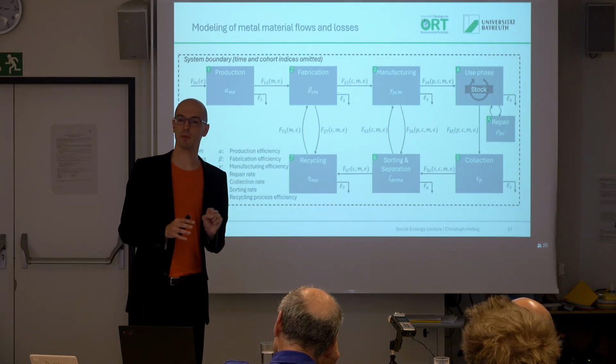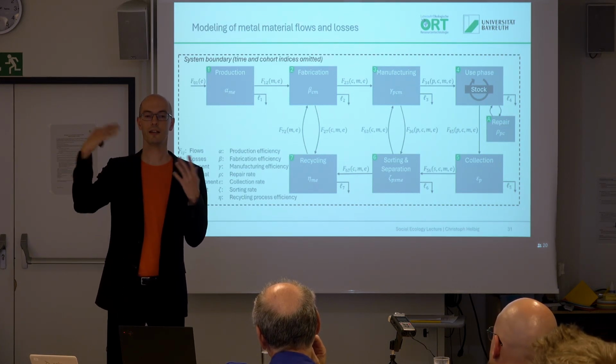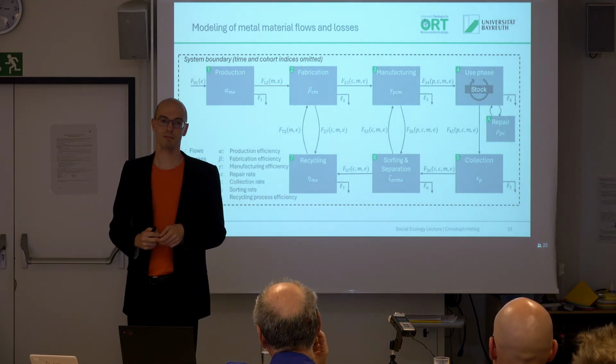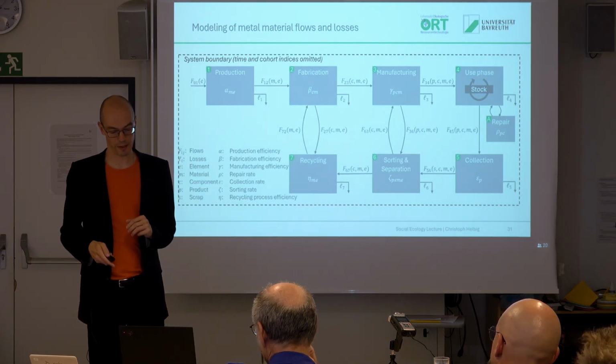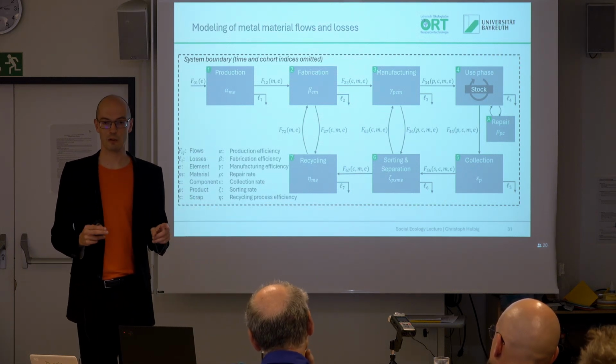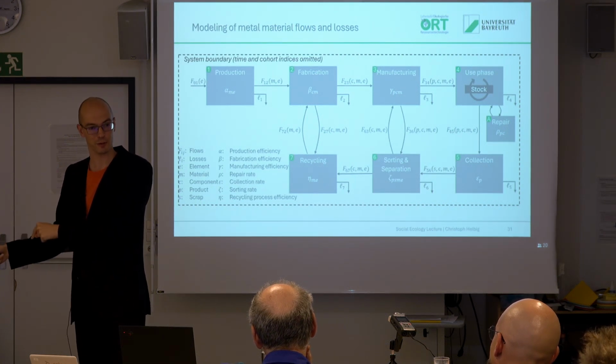Quite a bit of that we can recycle from EAF dust. So from electric arc furnaces, the zinc goes into the dust, and there we can get it back. With many other materials, they are much more problematic. So we need to be very specific about recycling efficiencies for minor metals, which they were actually not targeted for.